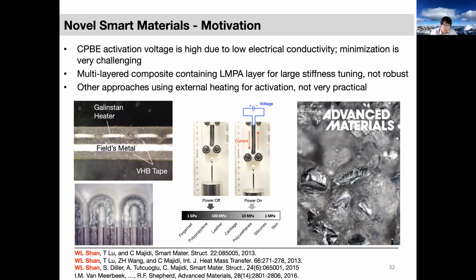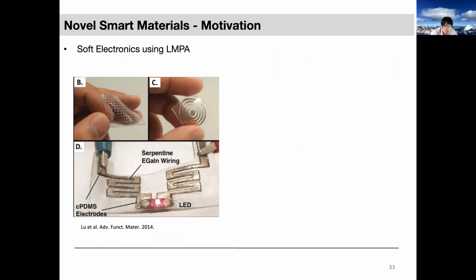Along the same line, almost in parallel, there have been efforts on soft electronics. The smart material we talked about earlier has tunable stiffness. But these ones are not tuning stiffness; they are soft, stretchable, and conductive. This is mainly to replace silicon electronics. These are efforts done by the CMU group. You can see they use gallium alloy-like inks. Either they have channels like this, or they use a laser engraver, and they can make these soft electronic devices.